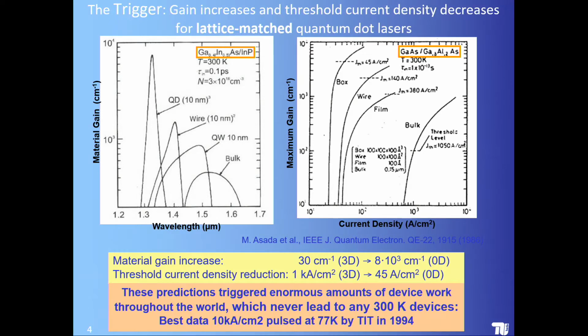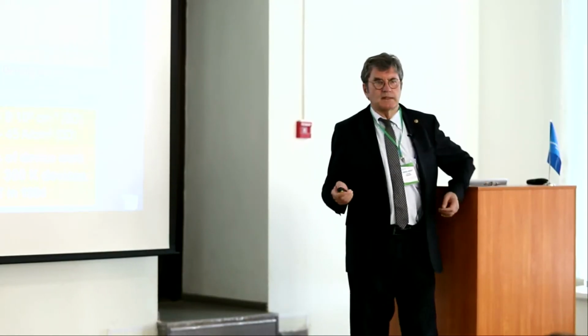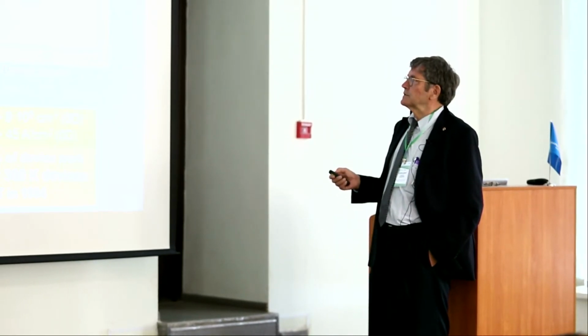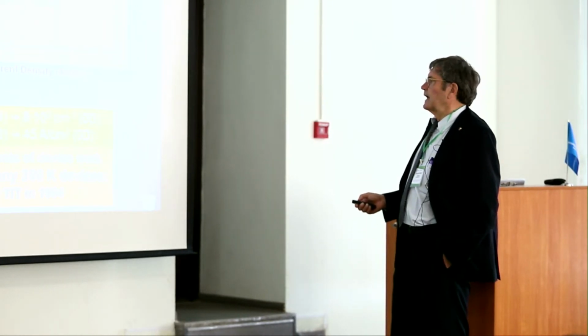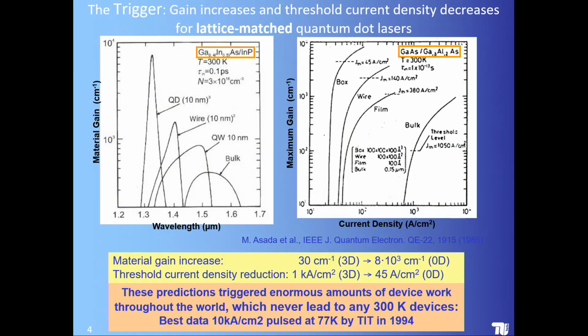He calculated the gain and the threshold current density for a number of materials. For one material, gallium indium arsenide on indium phosphide, that is a material which is today used for long wavelength lasers, for the intercontinental internet at 1.55 micrometer. And he calculated that the gain increases if you go from bulk material, indium gallium arsenide, over quantum wells, quantum wires to quantum dot. It increases from 30 reciprocal centimeters to about 8 times 10 to the third, 8,000. Yeah, so it's an increase of about 2 orders of magnitude.